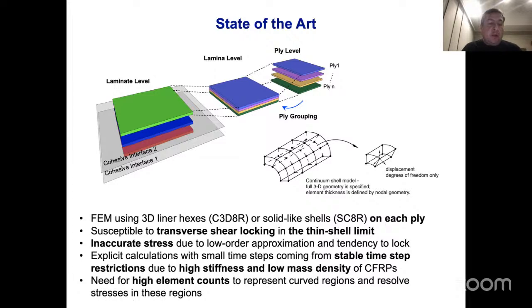But if you carefully look at this technology, you see that these are susceptible to what's called transverse shear locking, especially in the thin shell limit, where each ply becomes very thin. You get fairly inaccurate stresses due to the lower order approximation that's involved. These are only piecewise linear finite elements, so you get stresses that are only constant on each individual element.